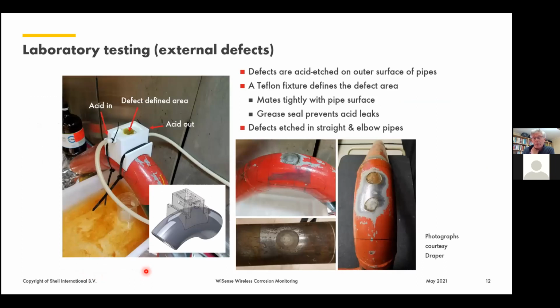A few pictures on background testing. I like to present this because testing a permanent monitoring system is not that straightforward. And this is an example of etching a pipe. Why etching? Well, that is because we have a magnetic technique that is sensitive to cold work. So if you start machining defects, you introduce magnetic fields. And particularly in the beginning, we didn't want that disturbance. We later learned you can minimize it to a large extent, but etching a defect gives you the most natural introduction of a defect without disturbing magnetic fields.